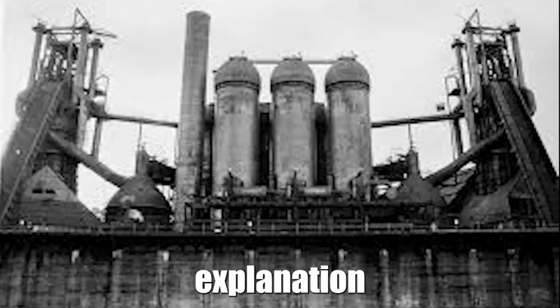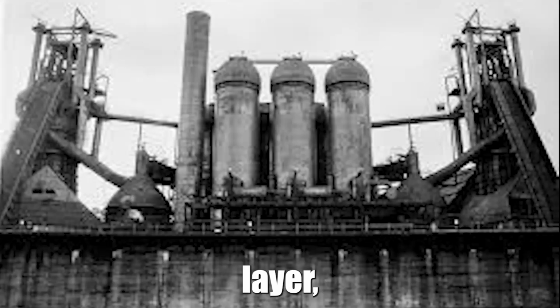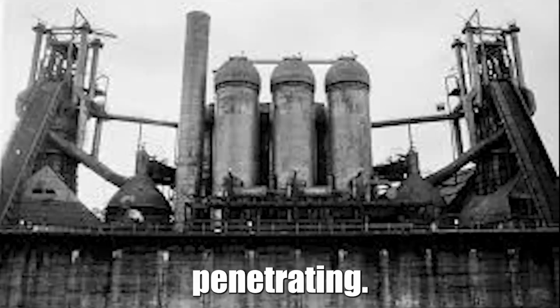The metallurgical explanation for the superior performance came down to how different manganese levels affected crack propagation. When the armor-piercing projectile impacted the high manganese surface layer, the tough steel absorbed kinetic energy through plastic deformation rather than brittle fracture. The manganese-enriched zone effectively functioned as a sacrificial layer that blunted the projectile's penetrator, converting its kinetic energy into heat and deformation rather than allowing it to maintain its shape and continue penetrating.